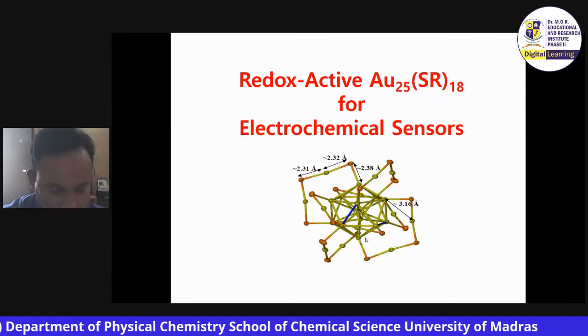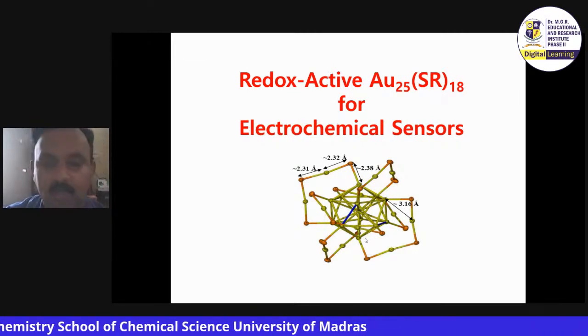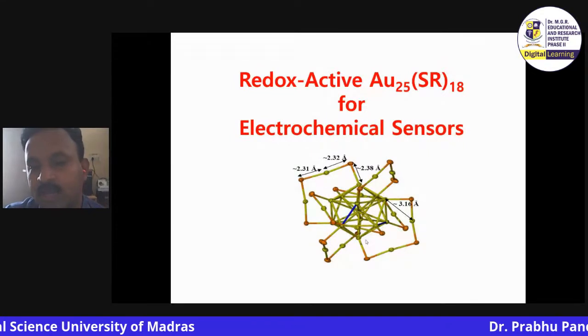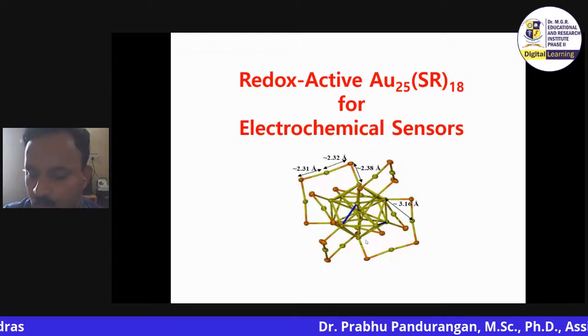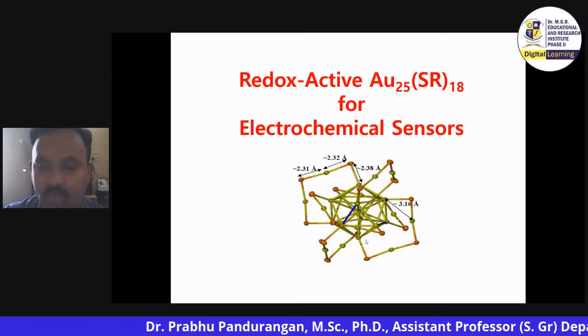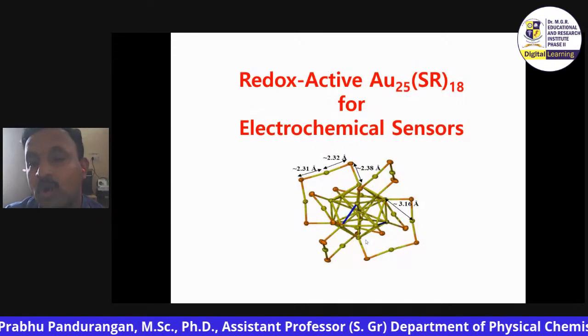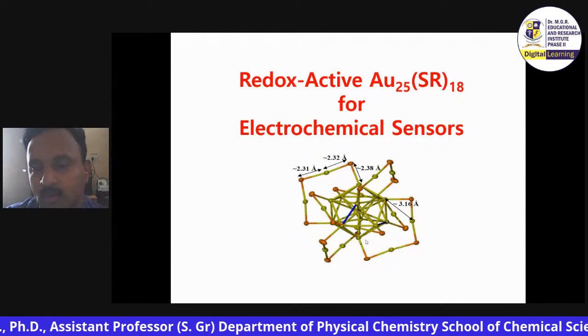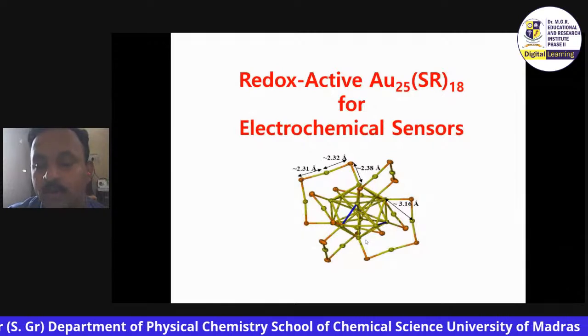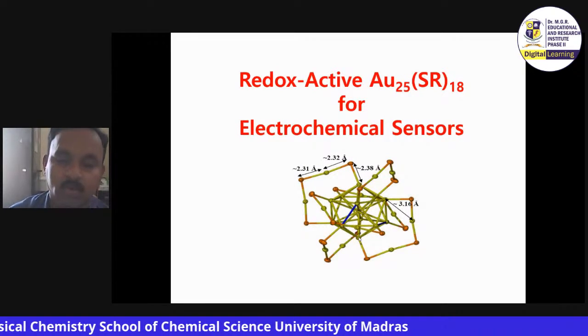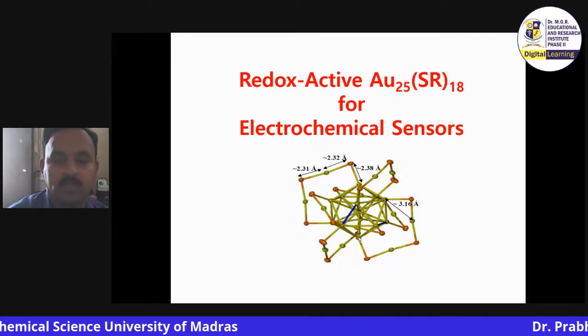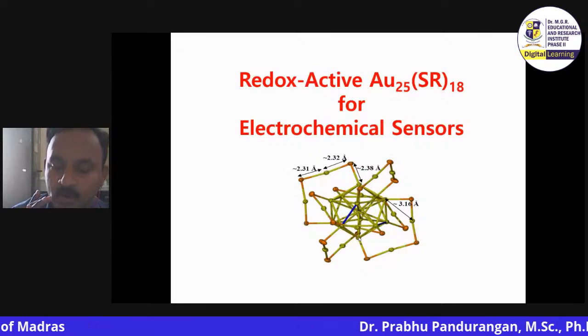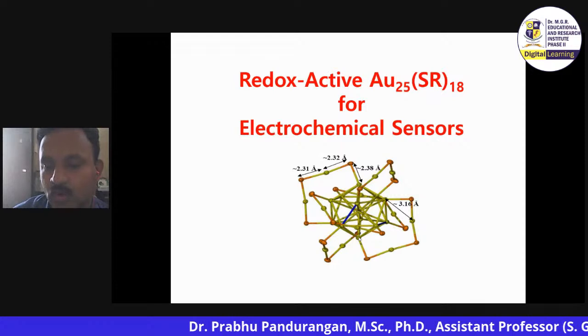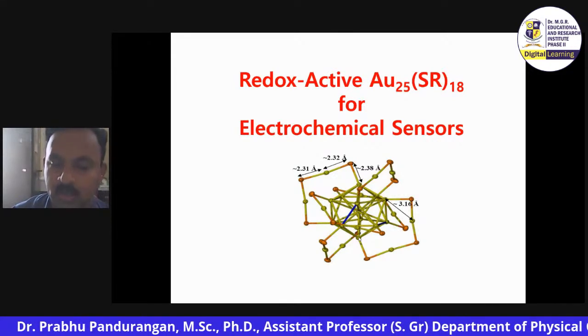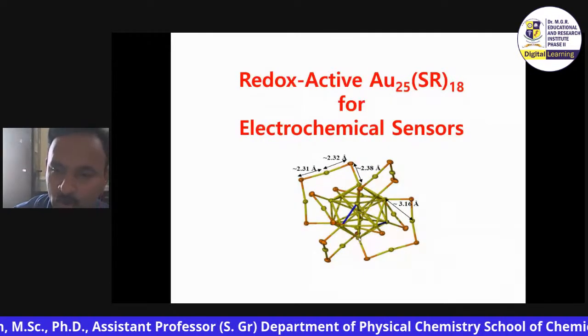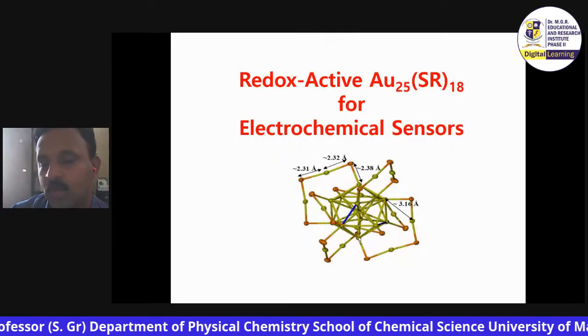Right. So what is the use of this cluster separation? Dr. Prabhu, if you ask me, each size will have a different and unique property. Many people would have worked on gold nanoparticles and taken electrochemical responses. You can see a gold particle even at a size of 1.2 or 2 nanometer will not establish any redox behavior. What is redox behavior? If the delta Ep is equal to or less than 60 millivolt. So to the beauty of this gold 25, gold as such at 1.2, 1.3 will establish a quasi-reversible response; you will not get a redox peak. Here, for gold 25, for the first time, we were able to achieve 2 redox peaks.